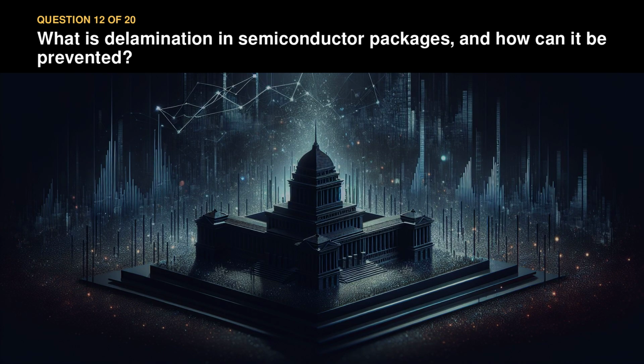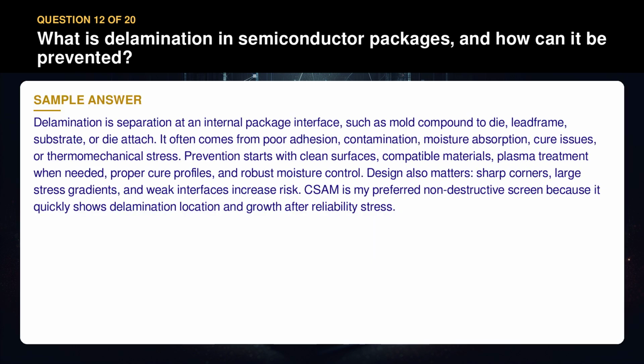Question 12. What is delamination in semiconductor packages, and how can it be prevented? Delamination is separation at an internal package interface, such as mold compound to die, lead frame, substrate, or die attach. It often comes from poor adhesion, contamination, moisture absorption, cure issues, or thermomechanical stress. Prevention starts with clean surfaces, compatible materials, plasma treatment when needed, proper cure profiles, and robust moisture control. Design also matters. Sharp corners, large stress gradients, and weak interfaces increase risk. CSAM is my preferred non-destructive screen because it quickly shows delamination location and growth after reliability stress.